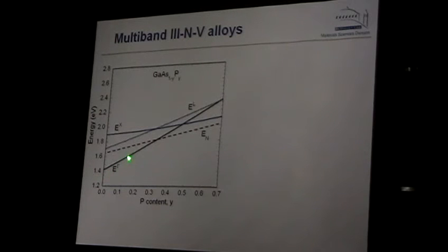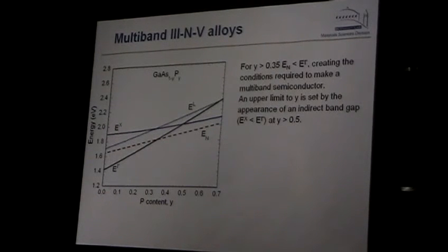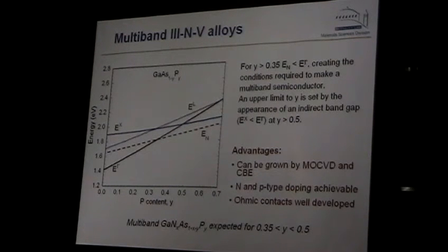So when we add phosphorus, we know it's a normal, well-matched alloy, the conduction band goes up, and finally it comes above the nitrogen level. The nitrogen level comes up as well. And this is the range where we are interested, because in this case, we hopefully could form this intermediate band. So we were interested in this range here. An advantage of this material, of course, is that it can be grown by MOCVD. So we don't even have to use pulsed laser melting in this case, because it has been demonstrated that it can be done by MOCVD.